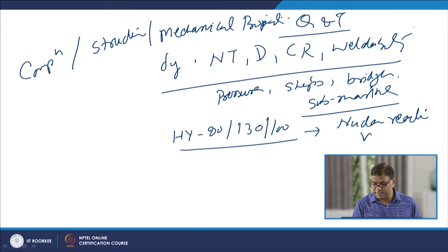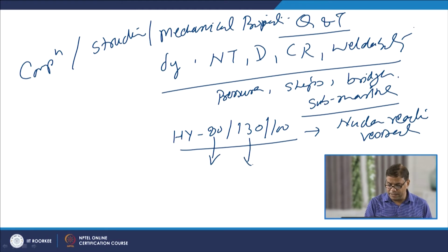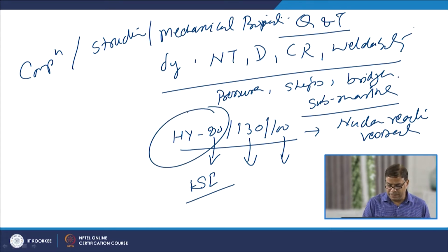reactor vessels, and here these numbers indicate the yield strength in KSI of these steels, like HY 80 means the minimum yield strength is 80 KSI of the HY 80 steel, and likewise for HY 100 it is 100 KSI yield strength, or 130 KSI yield strength for HY 130.